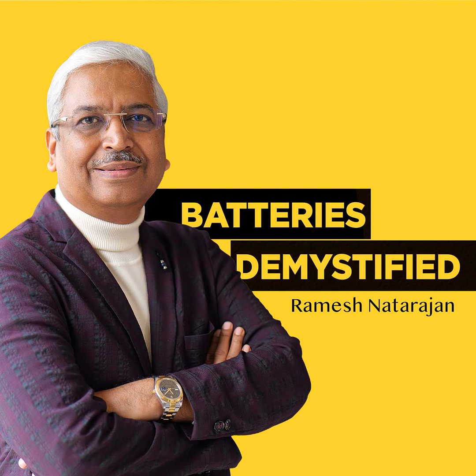Well, yes, but we also see that batteries prepared without any lignosulfonate die very prematurely. Even the oldest lead batteries, when they were designed with wooden separators, once those separators were replaced with plastic ones, the batteries died very quickly and they had poor performance. So we know the lignosulfonate is essential, both for cold crank and also for lifetime. Now, the idea that one loses lignosulfonate, either through precipitation or decomposition, I think that seems reasonable. I think that's what one might expect. And so adding more could explain why that prolongs the battery lifetime. Possibly. Yeah.